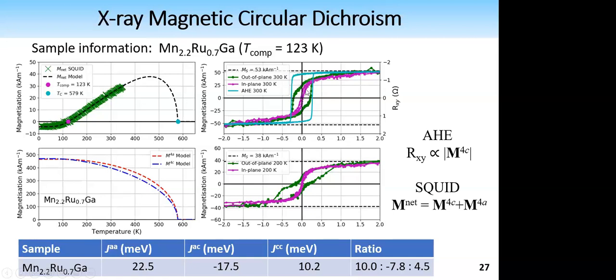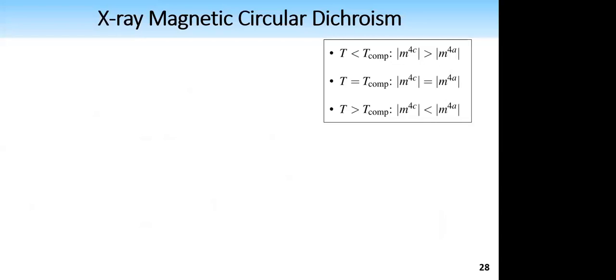Then if we take a look at the in-plane component, we see again this quite a strong soft component, which grows even bigger at 200 Kelvin, which is so big at this stage that you can't really even see the hard component. And of course, at the very bottom, I'm summarizing the exchange energies, where we again have the same hierarchy of exchanges as we've seen before. So now moving on to the XMCD data.